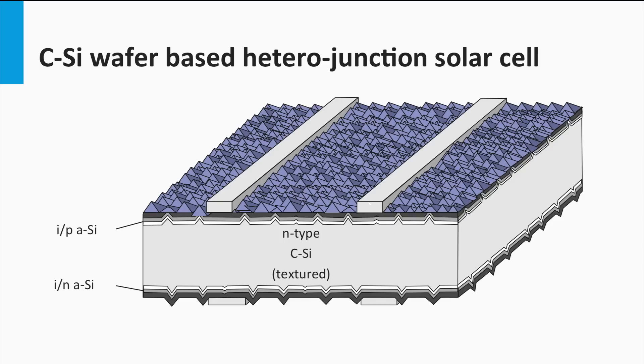How do the charge carriers travel to the contact? The conductive properties of the P-doped amorphous silicon are relatively poor. In the homojunction solar cells the diffusion to the contacts takes place in the emitter layer. In contrast, in a HIT solar cell this occurs through the transparent conductive oxide material, like ITO, which is deposited on top of the P-doped layer. The ITO is needed as the conductivity of the P-type layer is too poor. This results in such small diffusion lengths that a practical metal finger spacing cannot be achieved using the P-type layers.